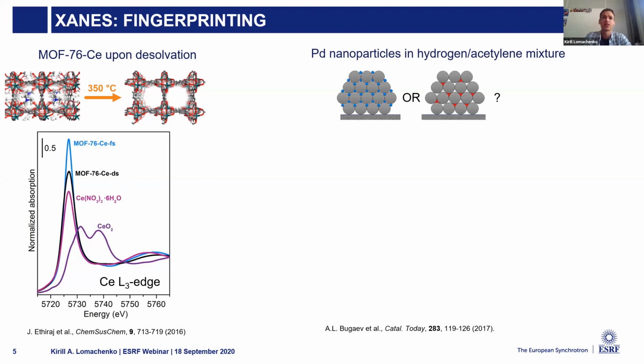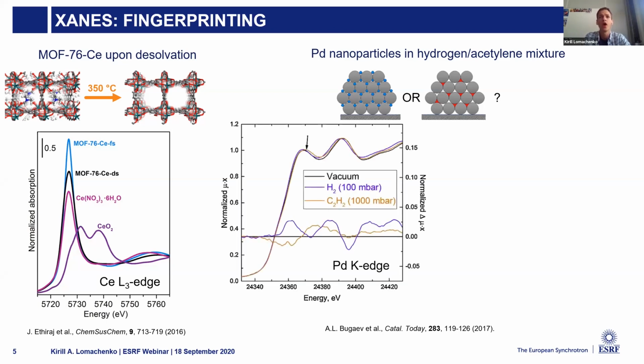Another example is with palladium nanoparticles. When we expose them to hydrogen, we form palladium hydride. When we expose them to acetylene, we form palladium carbide. But what happens if we expose them to a mixture of these gases at particular relative concentrations and particular temperature?